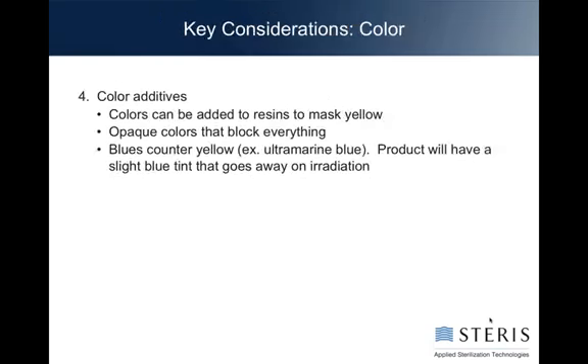Color. Most of the time, the first thing you'll notice with something that's been irradiated in general, but polypropylene exceptionally, is that it will turn yellow. Most of the time, not an appealing yellow, something that makes it look old or dingy. But there are ways to look at color. Color can be masked to get rid of the yellow. One of the most common things is sort of like if you can't beat it, join it, which is put something in there that's opaque and just snows out the yellow. That's why you see a lot of times colored caps, blue, orange, bright colors that are so intense they block out what you see as yellow.